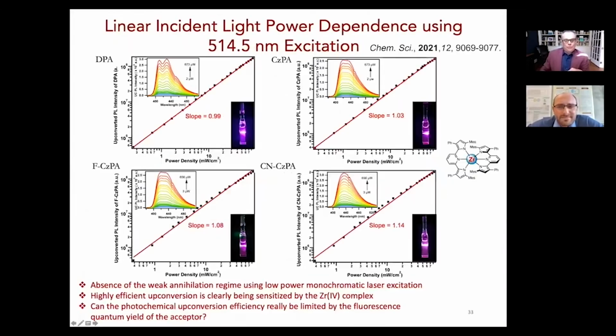is the absorption of the zirconium at the excitation wavelength here is 0.2. And we can get away with that because the extinction coefficient's really high. It's like 30,000. The lifetime's 350 microseconds. And it has all of these amazing properties that were amenable to varying the blue emitter and still getting really high efficiencies across the board. And clearly it works. Obviously, it's not the upconversion mixture that's going to solve any significant problems, but we wanted to prove that we could get to the 40% number with a molecular system under benign conditions. And I think that was really the driver of this sequence of experiments.